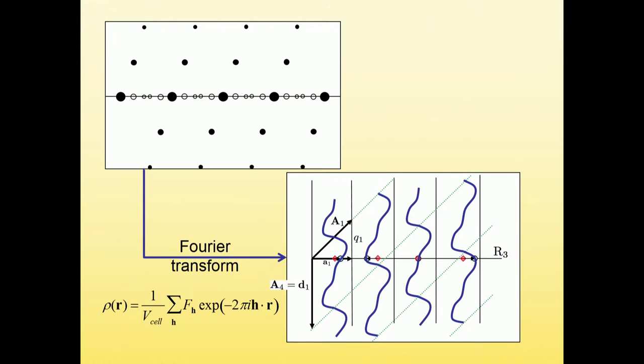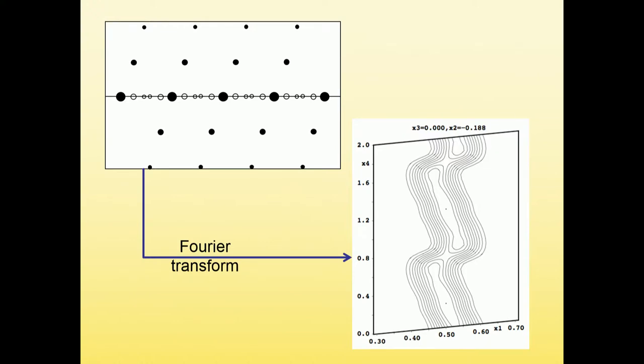What is important is that it may not be immediately obvious, but the two derivations that I showed you are equivalent and they both lead to the same result, and you can connect this superspace reciprocal lattice with this construction of superspace by the Fourier transform. So by the operation that brings structure factors on the reciprocal lattice of a periodic structure to the electron density in the periodic structure.